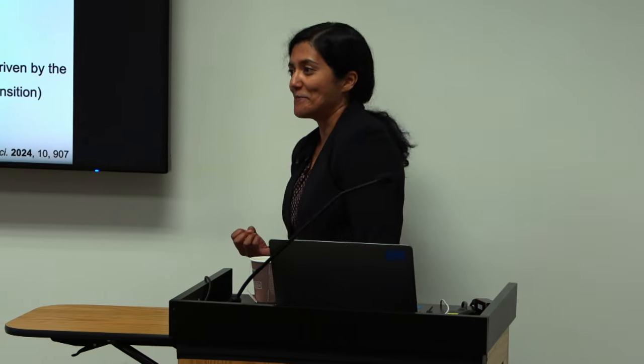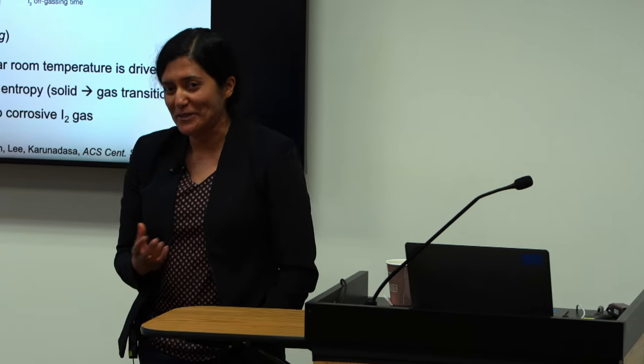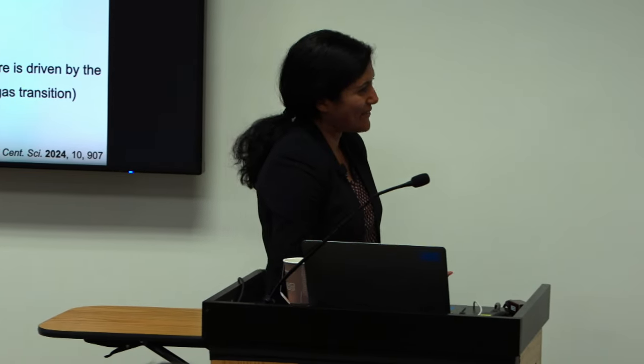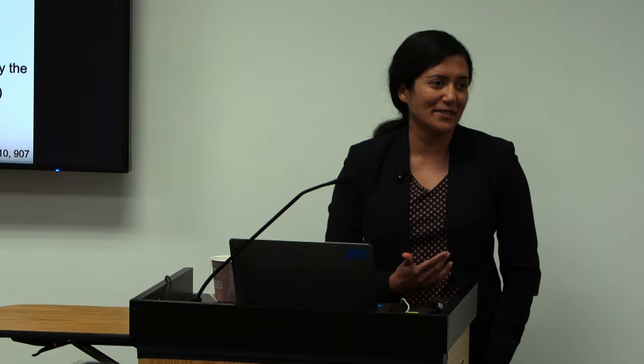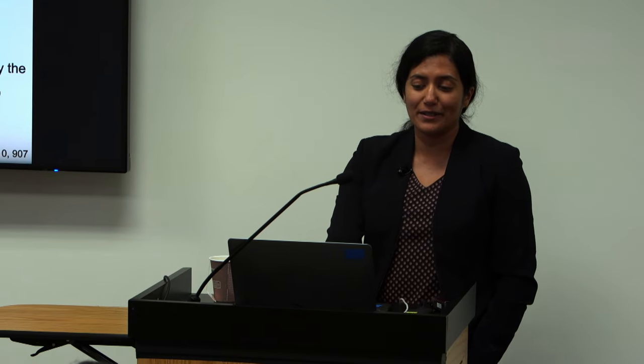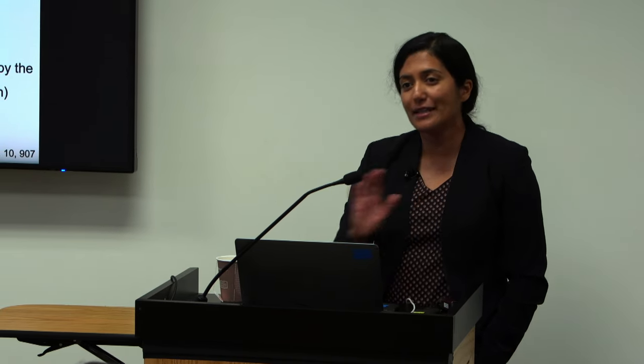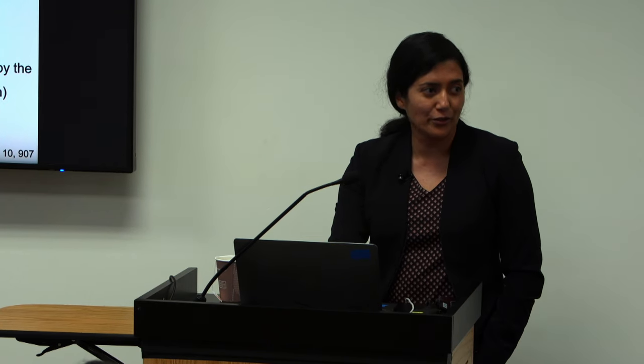So what's the solution? The solution is that we must find an encapsulant in which iodine does not dissolve. And iodine dissolves in pretty much every organic material. If you've ever worked with iodine, it's such a pain to deal with. It coats everything, absorbs onto everything. And we have to pay really close attention to the encapsulants we use for iodide perovskites, because we strongly believe that these entropy and enthalpy arguments we can make to any iodide perovskite, and this is going to be a general reaction. So that means we have to work with our friends in maybe polymer chemistry to come up with this encapsulant that's resistant to I2.